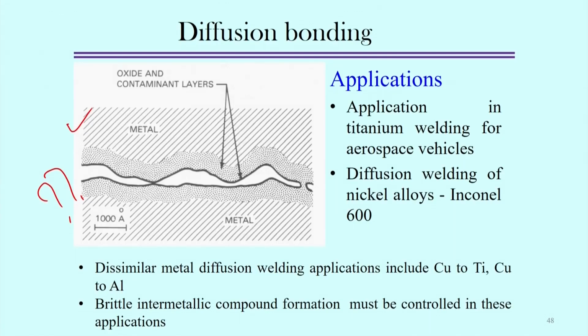We can find numerous applications of the diffusion welding process. One is titanium welding for aerospace vehicles. Titanium is a very hard material that is very difficult to weld in other processes, so diffusion bonding is an alternative method to get a good weld joint. Second is diffusion bonding of nickel alloys, for example Inconel 600. Sometimes dissimilar metal combinations such as copper to titanium and copper to aluminum are also joined by diffusion welding.